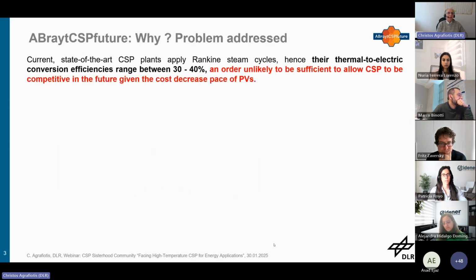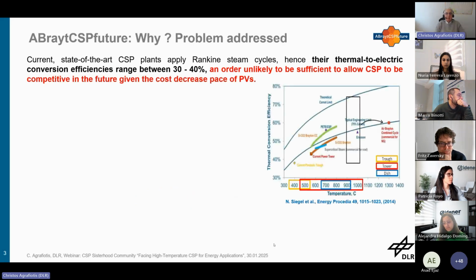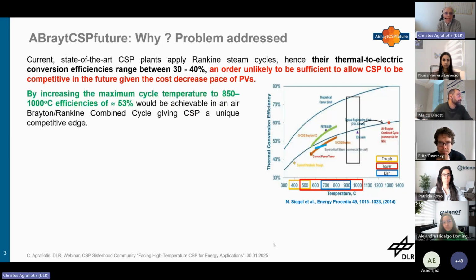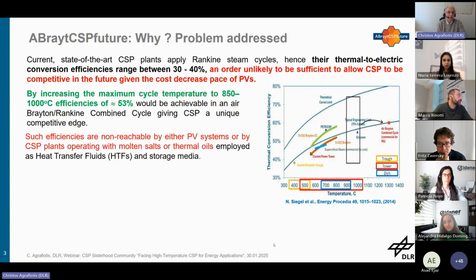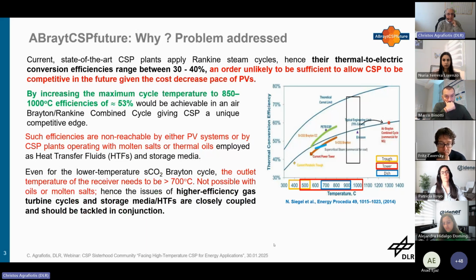Now, what is the problem that we try to address? As was already mentioned, current state-of-the-art CSP plants are inherently limited by low efficiency by using a steam cycle. So one idea for them to become competitive is to be able to use a combined gas turbine Brayton cycle with a Rankine cycle, which will go to higher efficiency. And this will give CSP a competitive edge because these efficiencies cannot be reached with either PV or CSP plants operating with molten salts or oils that are limited to lower temperatures. So even though for the recent supercritical CO2 Brayton cycles, we need to have a receiver which has a temperature output of the order of 700 degrees.